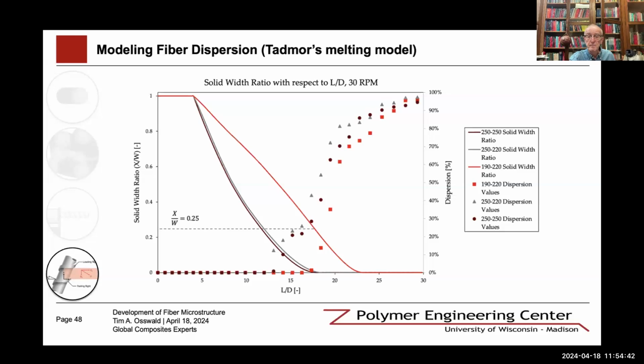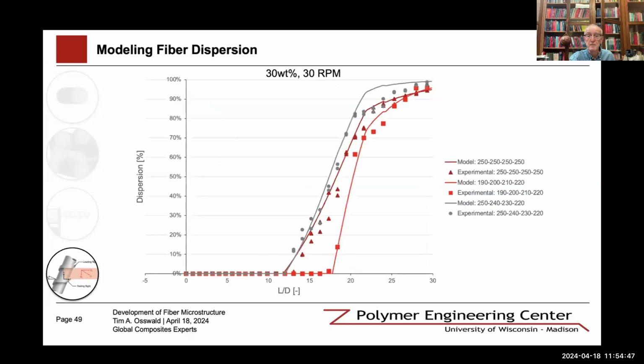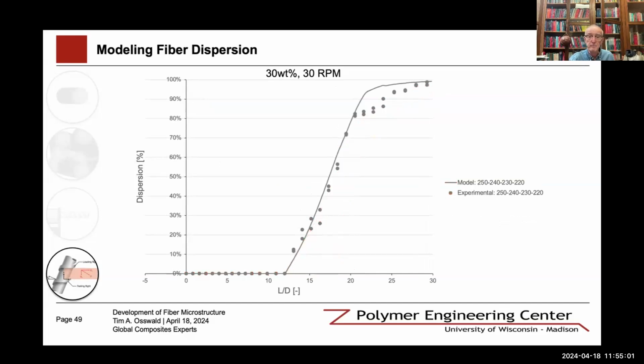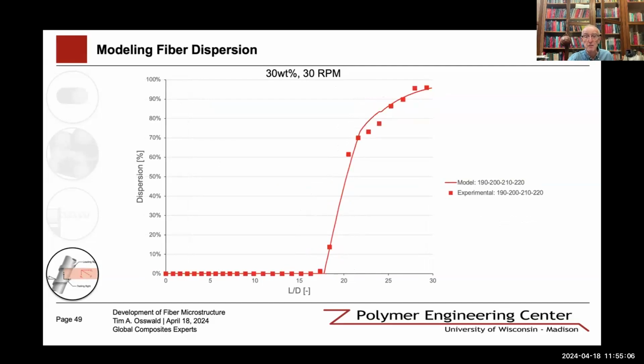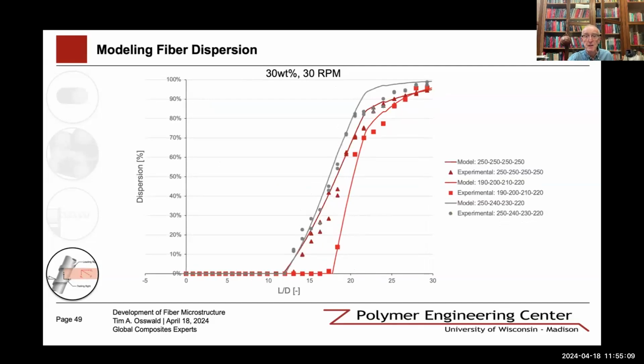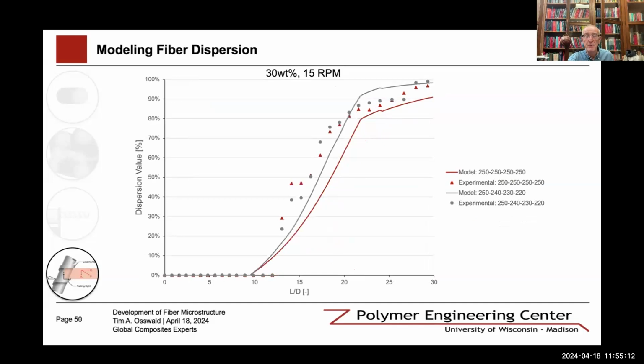So we can see that there for the different parameters. And then we used the melting model and the parameters in the extruder to compare the dispersion, and we can see at least we can compare dispersion quite well in the plasticating unit or in the extruder itself for different parameters. You can see several data here, so it works quite well. This is being currently written up for a paper in Polymer Composites.